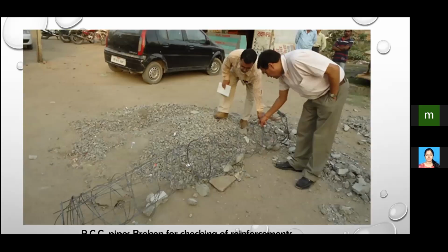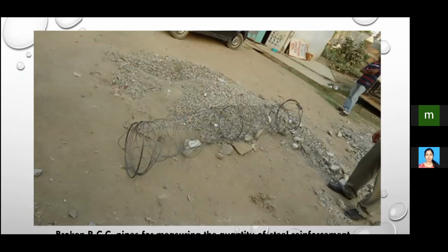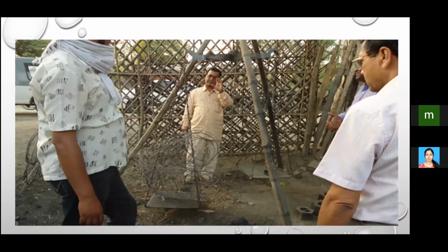Here you see the reinforcement cage, a pipe which was already damaged, or some pipes at random we took, and we got it broken totally. And then the reinforcement cage, we got that one, and that is visible here. Same thing for another pipe, and we were checking the weight. So, as you know, the reinforced pipe or RCC pipe, say for example NP4, non-pressure pipe 3, 4, like that gradation is there, which was documented in the tender, and which was supposed to be laid by the assigned contractors.